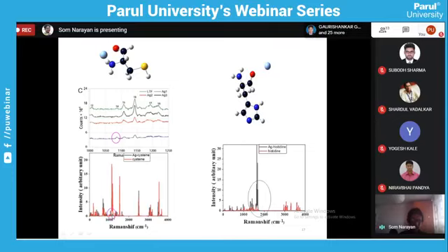is available in the Ag cysteine. In the case of cysteine, it is more, whereas as it is interacting with the Ag, this peak vanishes. So its intensity is much lesser as compared to the pristine one. Over here we can see that as we go from pristine to interacting with Ag, this peak disappears as it interacts with Ag. So we also compare that with all the three Ag molecules interacting with the